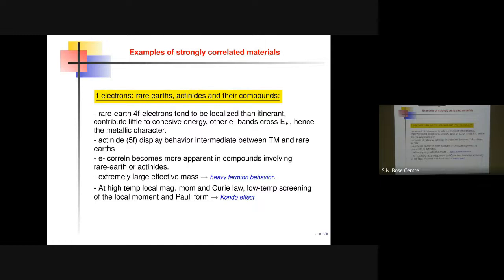F electrons. There are f electrons. They tend to be localized rather than itinerant. The correlation effect becomes much stronger than that of the d electrons. They contribute little to the cohesive energy because they are very localized. But many of these f electron systems are metals because of the presence of other electronic bands, not necessarily the f band. The actinides, which are 5f, display a behavior intermediate between transition metal and rare earth.